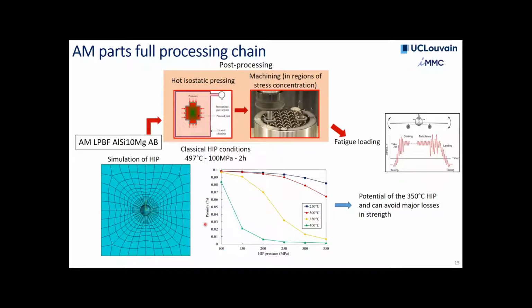to try to reduce the porosity quite significantly. In particular, we're interested in these large pores, as I was mentioning. And so here is the result of the simulation as a function of pressure and temperature. And here you can see the porosity reduces significantly at 400 degrees. But you can see that if you apply quite a significant pressure, well, at 350 degrees, it might be interesting. So the most common way is 100 megapascals, but here we've been working at 350 degrees.